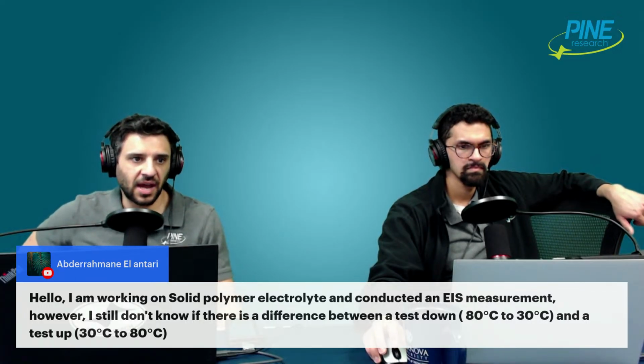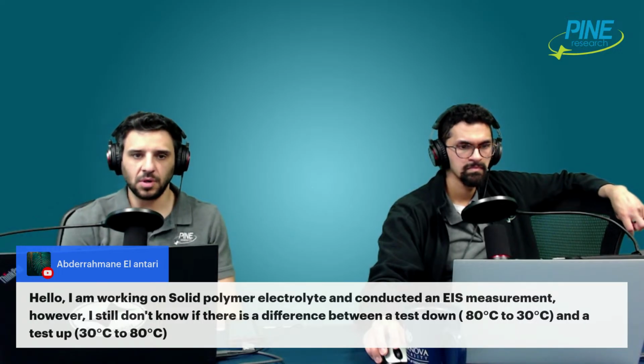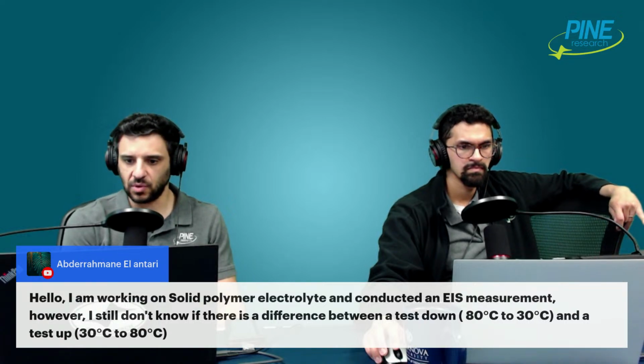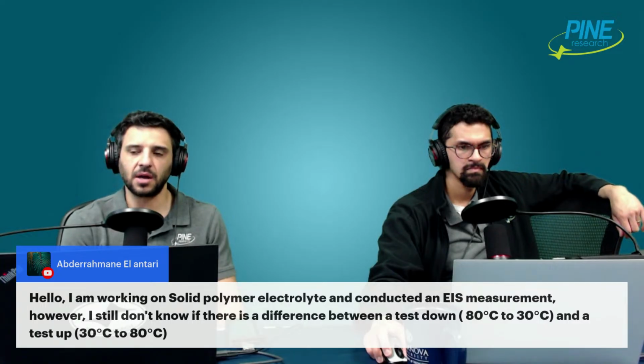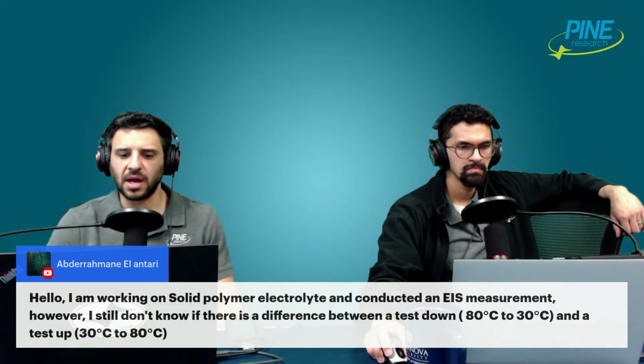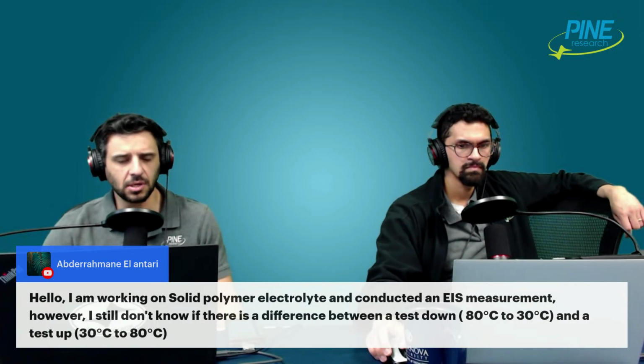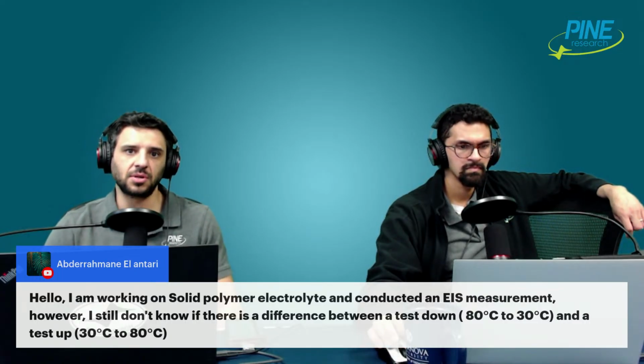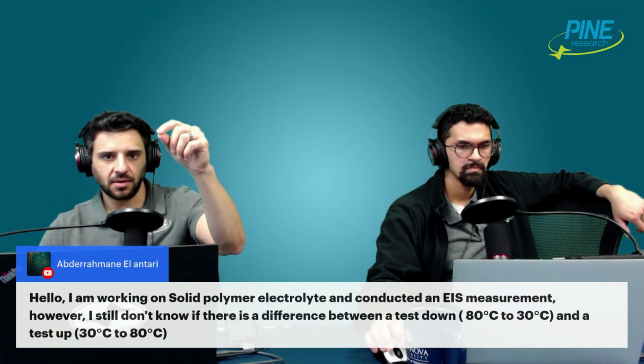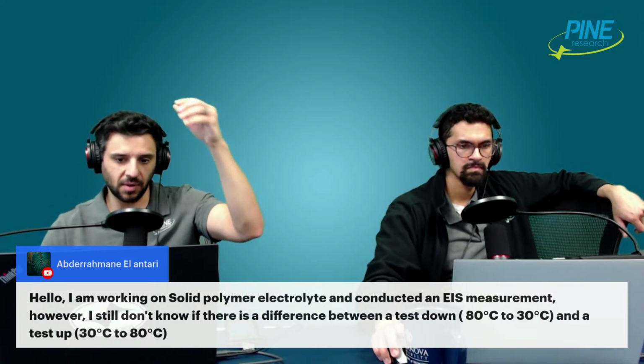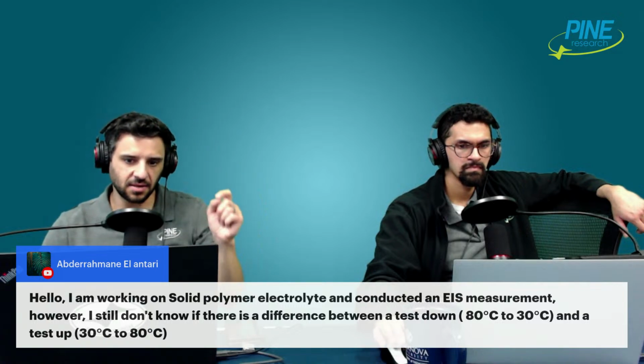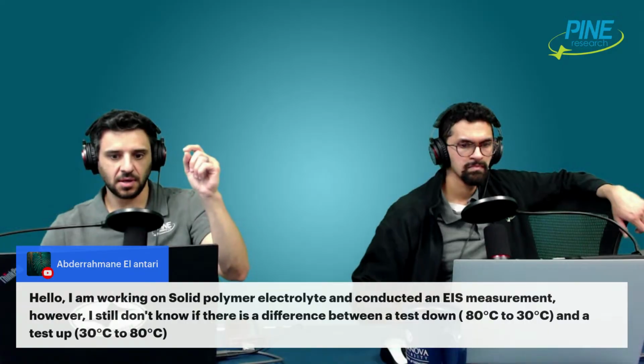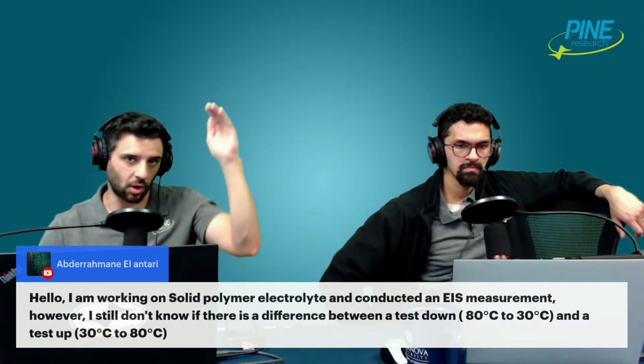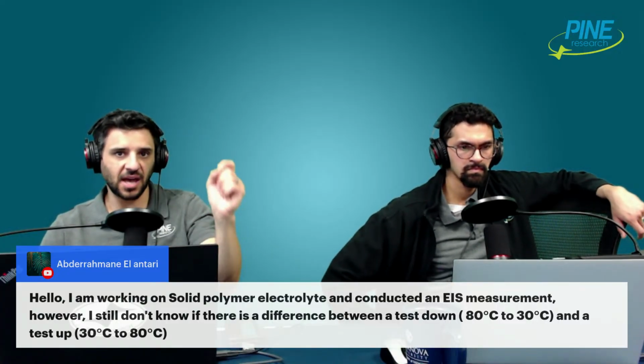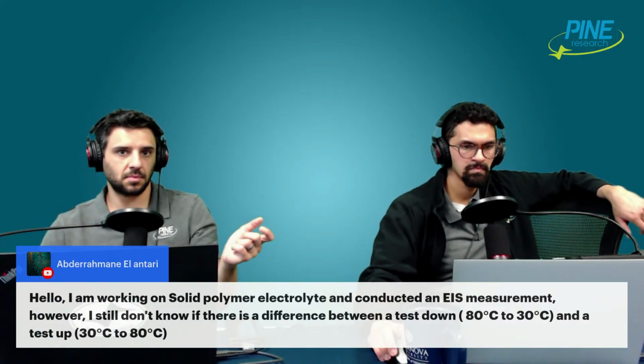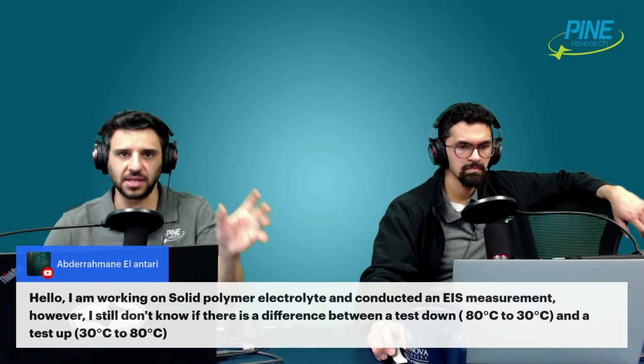And the ideal situation would be to do, for instance, I did something similar. Let me just give you an example. I did impedance diagnostic tests when I was a postdoc on some batteries. It wasn't solid polymer per se, but it was a similar kind of thing. I would do impedance at a variety of temperatures. So I would go 30, 40, 50, 60, 70, 80, and take impedance at each of those. And then I'd go similar to you, 80, 70, 60, and then I'd go 50, 80, 20, 70, 40, 30. I'd jump around. And I'd try to make sure that whether I went from down to up to down, or all over the place randomly, the data at each temperature was the same, or within reason, and then you can average it.